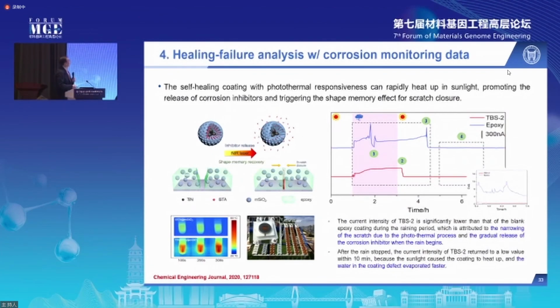And finally, we have also combined this with corrosion monitoring tests to understand how self-healing coatings evolve over time in real surface conditions. So this is an example showing that the coating has 2 parts, basically. The resin part is a thermal-responsive shape memory polymer, which can heal surface scratches by heat. It also has fillers, core-shell structure fillers with titanium nitride cores and mesoporous silica shells infused with corrosion inhibitors.